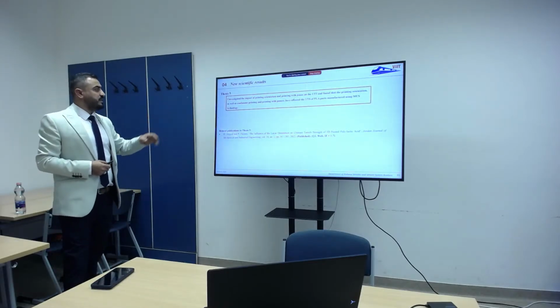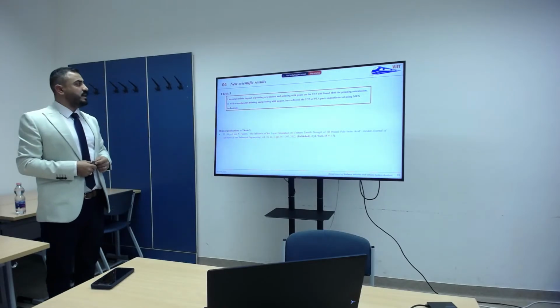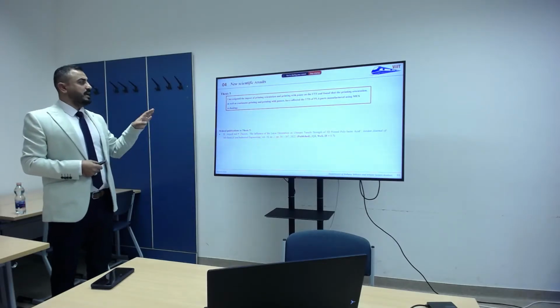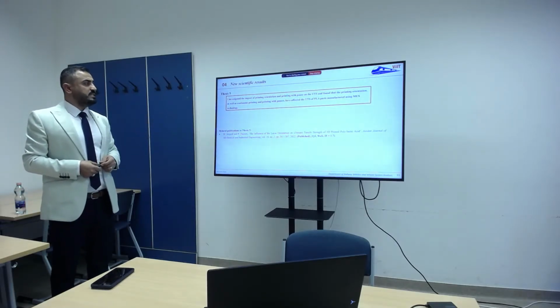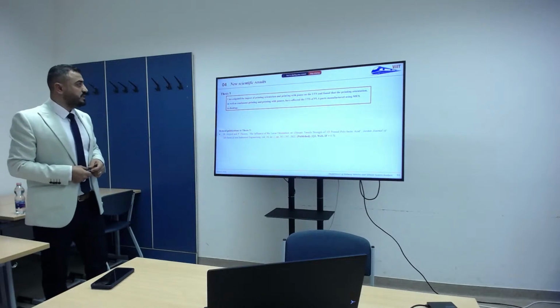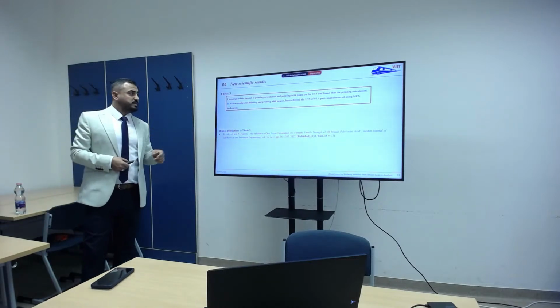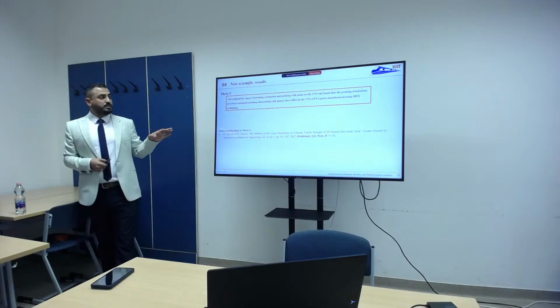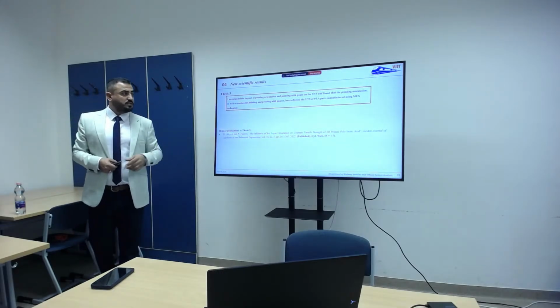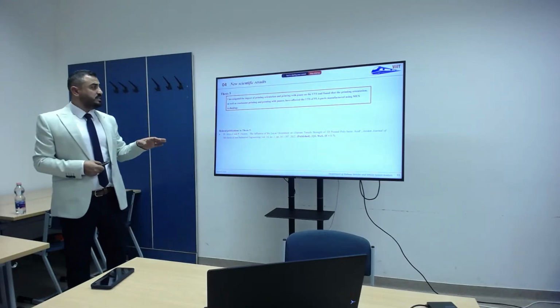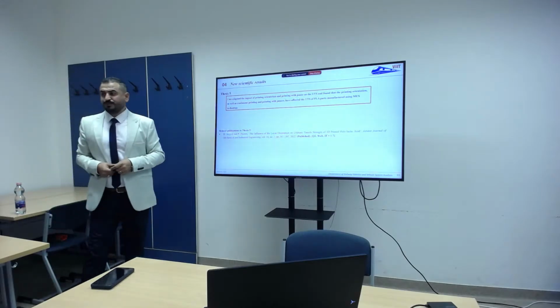So thesis number 5 stated that I investigated the impact of printing orientation and printing with pauses on the UTS, and found that the printing orientation as well as continuous printing and printing with pauses have affected the UTS of PLA parts manufactured using material extrusion technology.